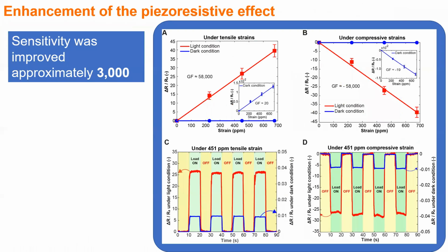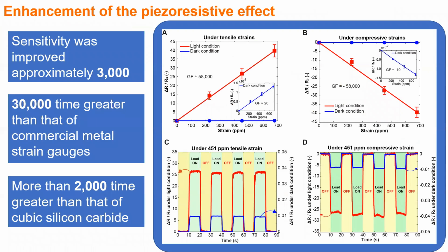By using the optoelectronic coupling, the performance of the piezoresistive effect has been significantly improved. For example, as you can see on the slide, under the dark condition, the K factor of the silicon carbide on silicon heterojunction is about 20, and under the light condition with the optimal tuning current, the K factor of the heterojunction structure has been improved up to 58,000. This is approximately a 3,000 times improvement.